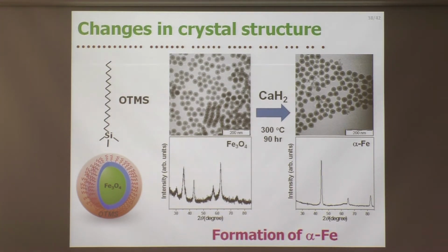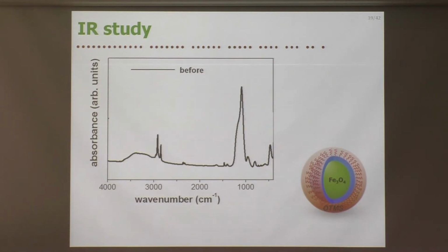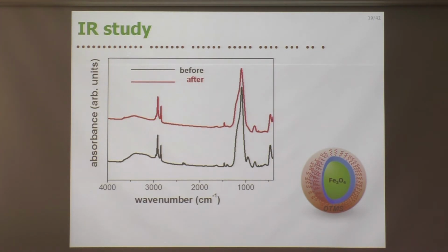Then, how about the surface organic molecules? We carried out an infrared study. Here is the IR pattern before reduction—we can see the absorption peak from the alkyl chain. After the reduction, as expected, the absorption pattern from the surface alkyl chain still remains. With these results together, we can say this strategy works.